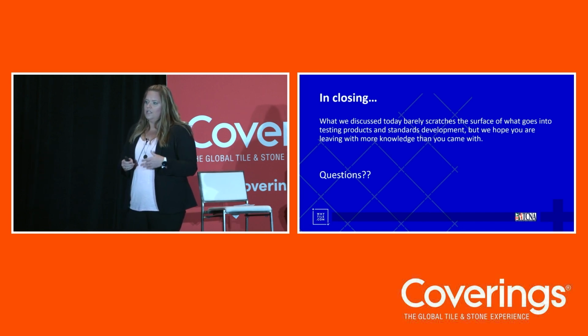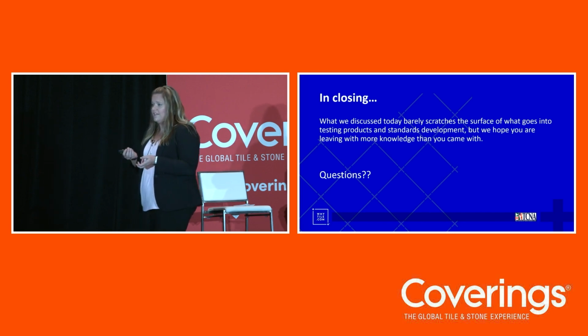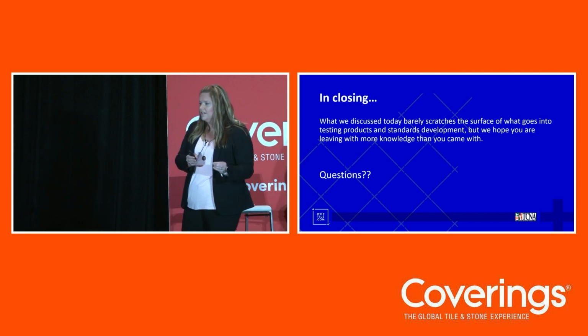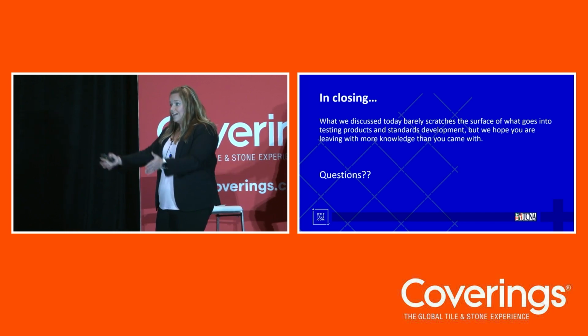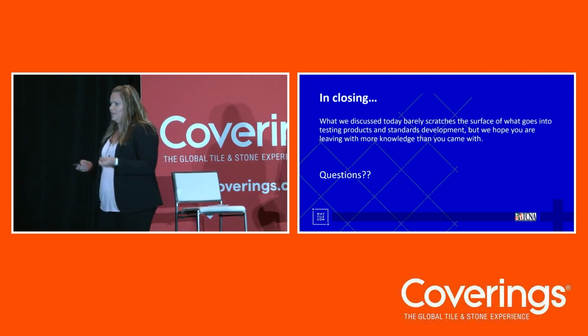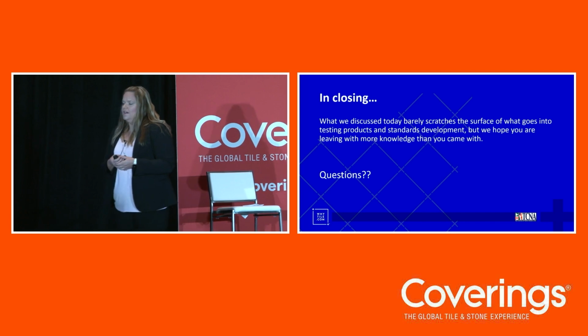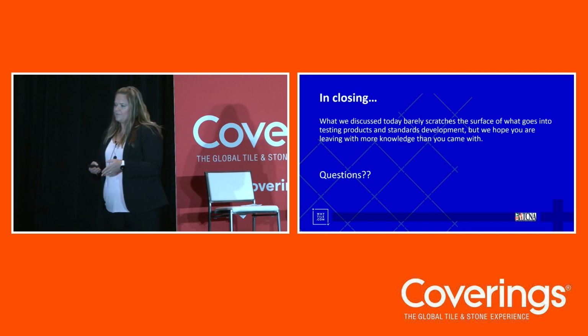There's also a chance that there's something else on the surface that's holding the stain there that's not necessarily an issue with the tile, but there's just something that's gotten on there. So occasionally, if we can't figure it out with a new piece, we have to ask to cut a piece out from the field. If it's really a bad issue, we've got to pull a piece, and we can start analyzing it with different chemical analysis of the stain, so we can figure out what is there, and is it something that's just on the tile that's holding it there, or is it the tile itself?